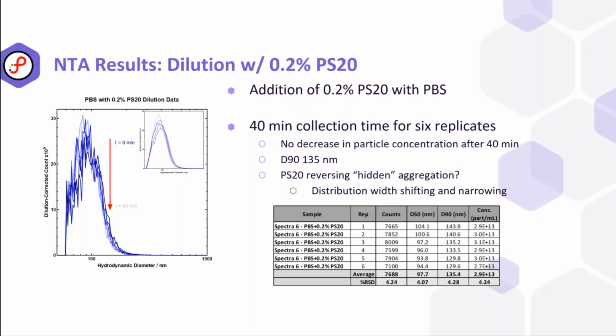So here we added in 0.2% PS20, and we see that the concentration really hasn't changed at all over 40 minutes. So it looks like we've been able to stabilize this. The D90 is a little bit lower than it was initially for the dilution.